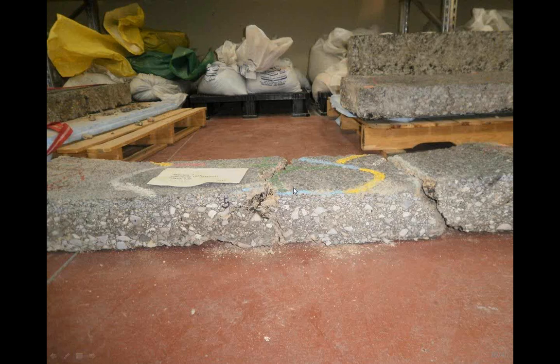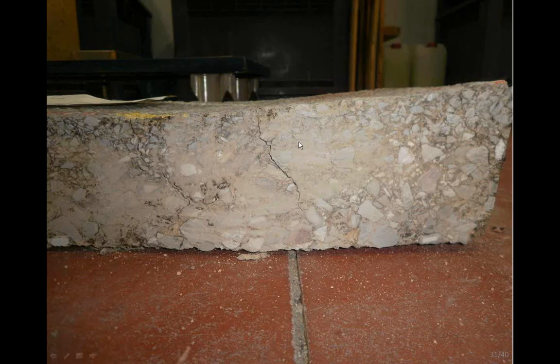One interesting thing is that not in the center of the wheel path, but like 50 centimeters, 70 centimeters, or 60 centimeters from the center of the wheel path, we have this type of cracking. And probably you can see this better here. Again, this is like 50 centimeters far from the center of the wheel path, and there was a shear cracking. I mean, this type of shear could be caused by shear forces.